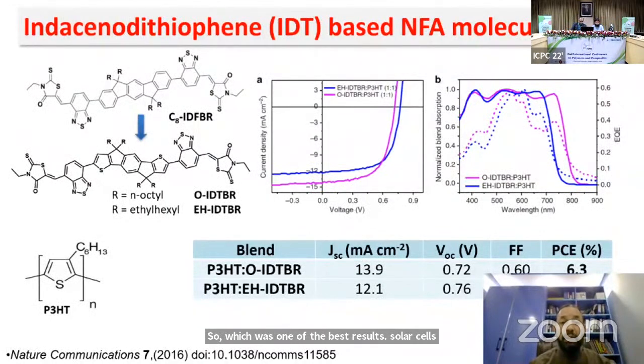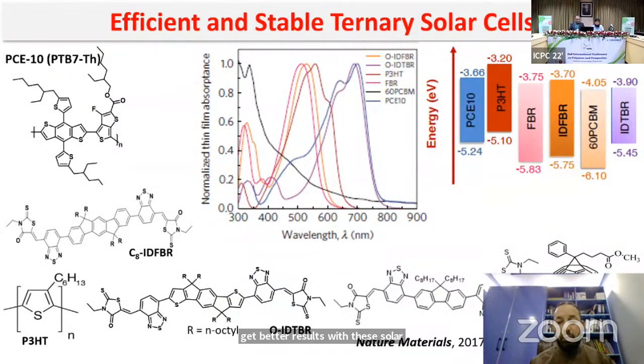But for us the question was whether there was any other possibility to improve further and get better results with these solar cells. We decided to try something different. At that moment, we decided to see if we could improve the morphology by adding a third component. Instead of using two components, we went for ternary solar cells, using three components in one layer. By carefully looking into the energetics of these molecules, we used two acceptor molecules and P3HT as the donor polymer in the devices.